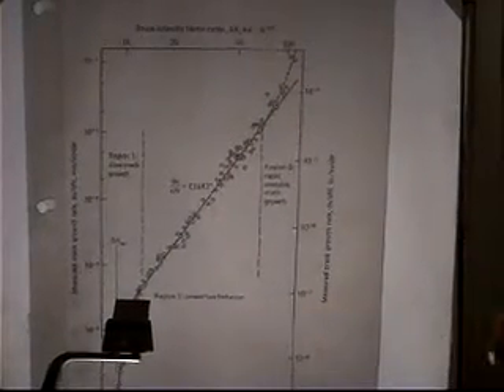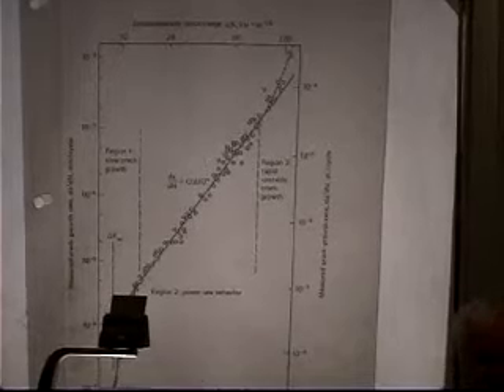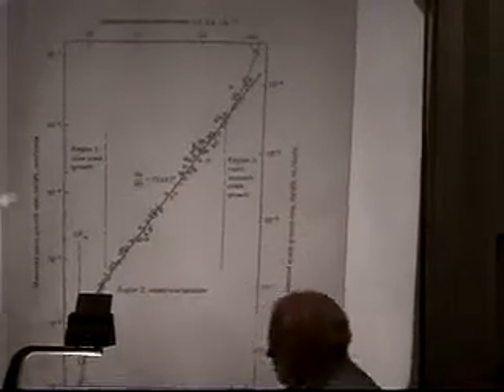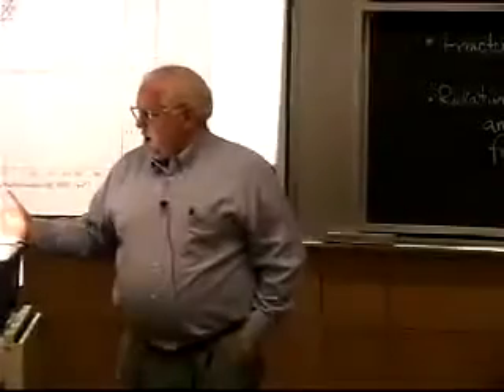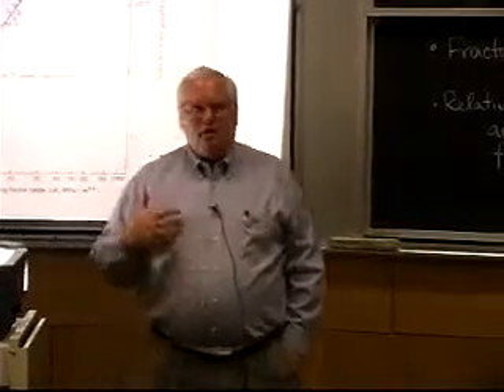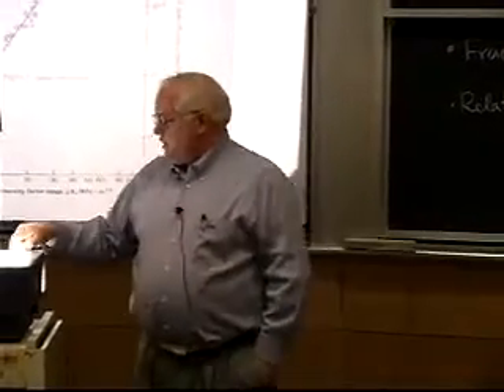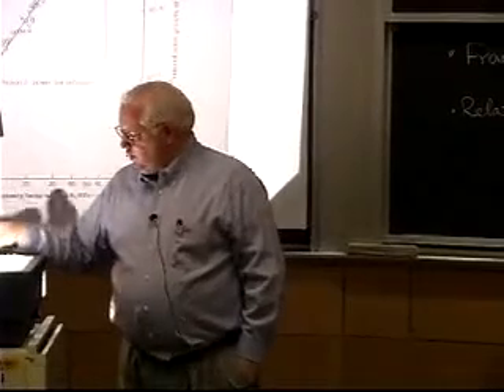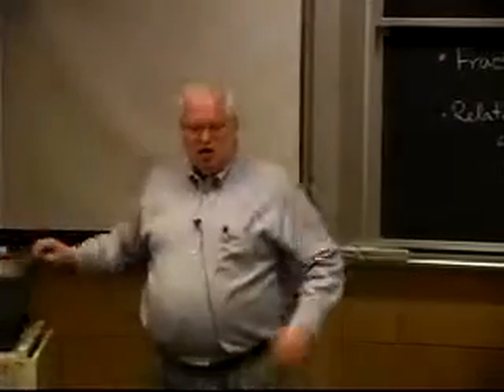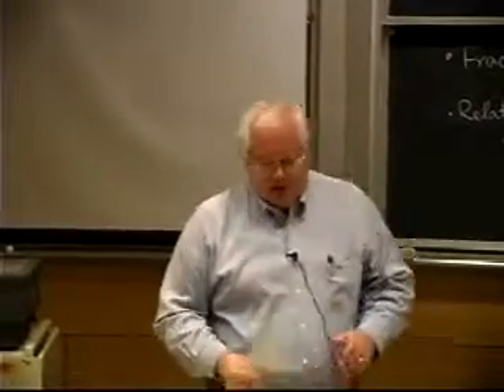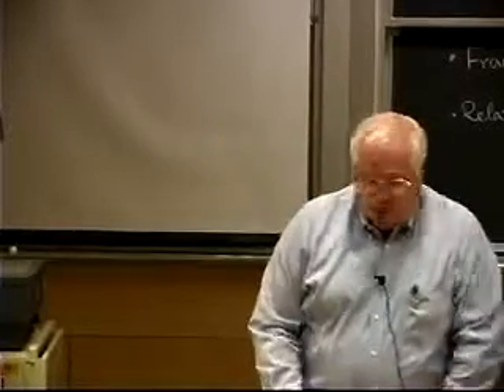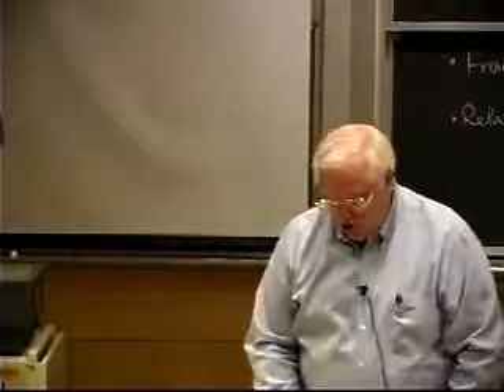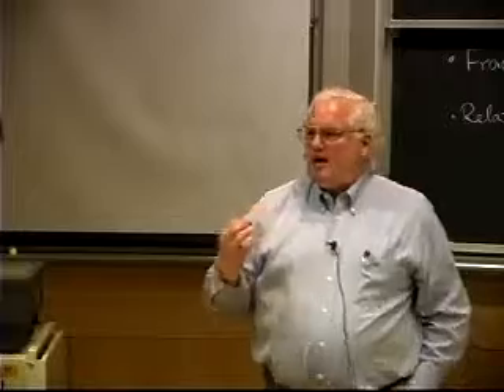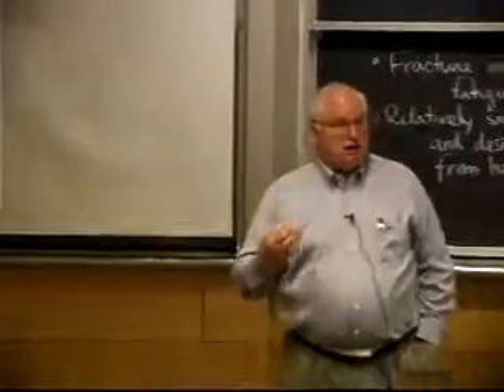This is the crack growth rate. If I know the stresses in the structure, I can predict how many cycles it will take. I just have to integrate this curve, and it turns out you can integrate this curve, and people do it. I've done it. And you'll find how many cycles it will take, da/dN, at a given stress level, for the crack to start from, let's say, 1/8 of an inch in size. Why 1/8 of an inch? Because 1/8 of an inch is a typical flaw size that can be readily detected by most non-destructive testing techniques.